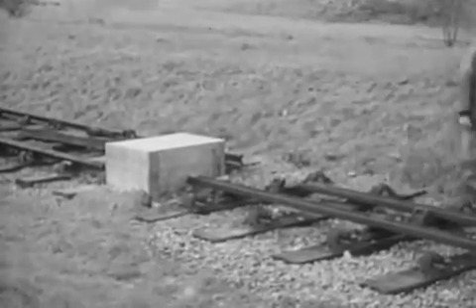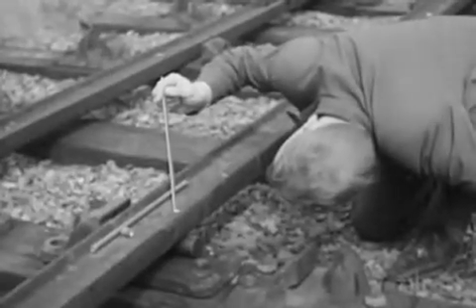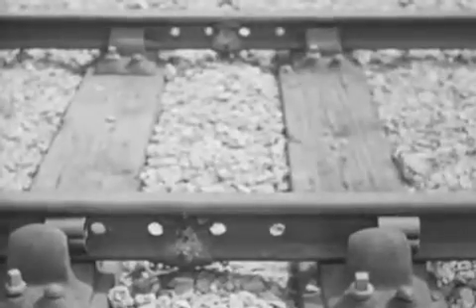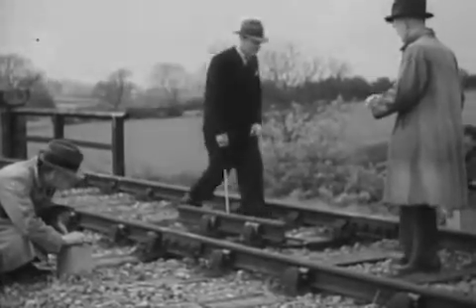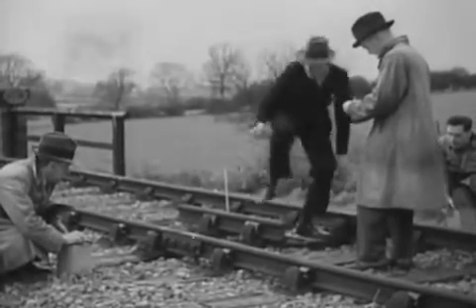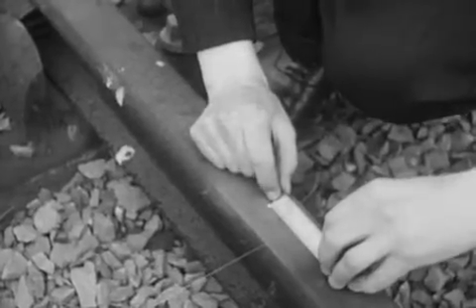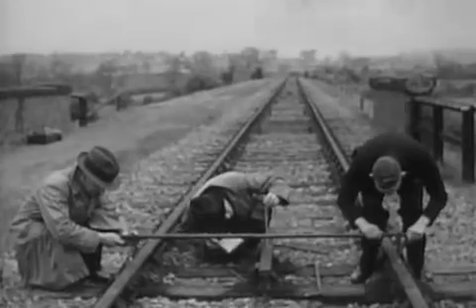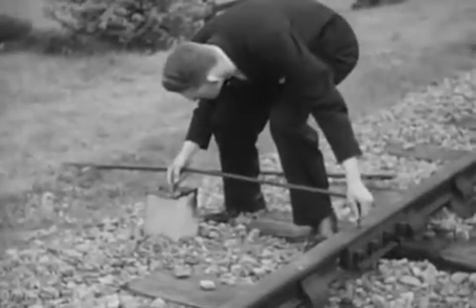Another interesting investigation is that which is being carried out at present at Medbourne on the welding of long sections of track. 2,200 feet of track over which no traffic passes was welded into one solid length. A control length of free track is established nearby to provide a comparison. The experiments are directed towards determining the expansion and contraction and the buckling of the track caused by temperature variations. Careful measurements of all track movement and stresses are taken throughout the welded length each time a party of research workers visits the site. Measurements are taken during hot and cold weather. The experiments will probably be of long duration because they depend on the uncertain English climate.